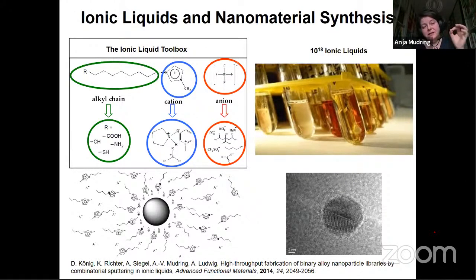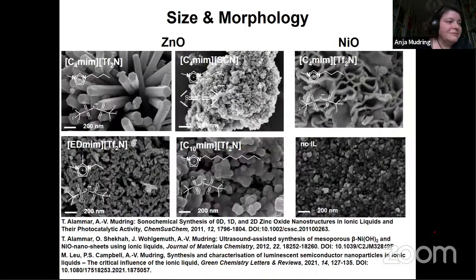And with TEM, we have directly imaged the particle in the ionic liquid itself. Of course, you have to have colleagues that are brave enough to put a liquid into a TEM, a very expensive machine. The good thing is many of them have a really small vapor pressure so that you can handle them. And this was one that we tested before we did that image in Bochum with colleagues from material science there.